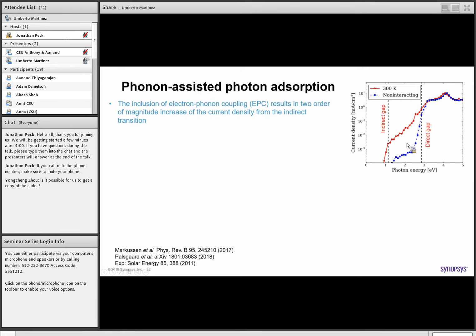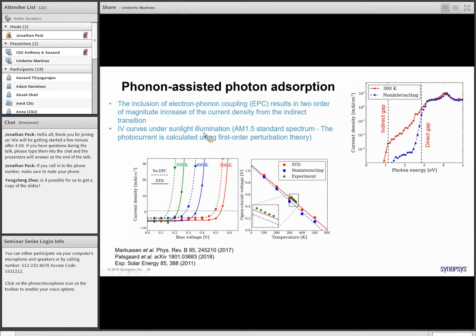So here you can see these two lines where we show the current density. If we don't include electron-phonon coupling, you have the blue line. As soon as we switch on this interaction, in this case at 300 Kelvin, you can see that at the energy close to our indirect gap, you already have an increase of a couple of orders of magnitude in your current density. We can now use